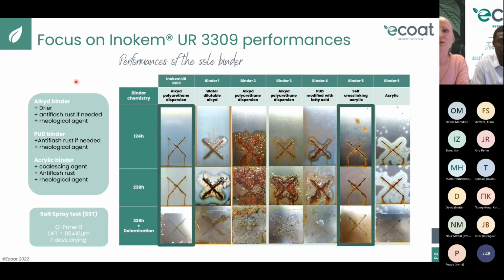To start, we exposed 3309 in a salt spray device with no formulation, in comparison with other technologies such as water-reducible alkyds, alkyd polyurethane dispersion, polyurethane dispersion, or even some acrylics, for example. And we can see that after 238 hours of exposure, Inokem UR 3309 showed very good performance, better than most of the other technologies. Indeed, we can see some corrosion development for most of the binders at only 124 hours. Also, we can say that the 3309 is equivalent to the cross-linking acrylic market reference for metal protection. It is equivalent in performance, but not in price for sure.